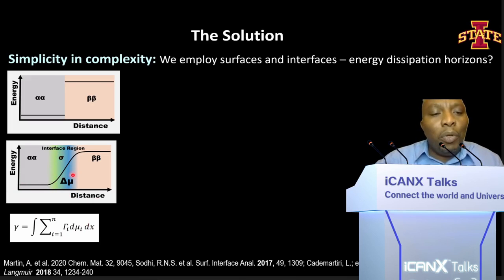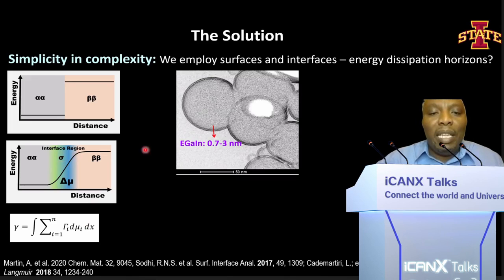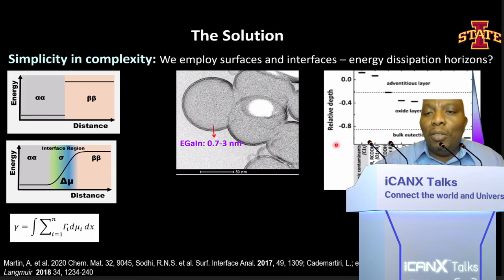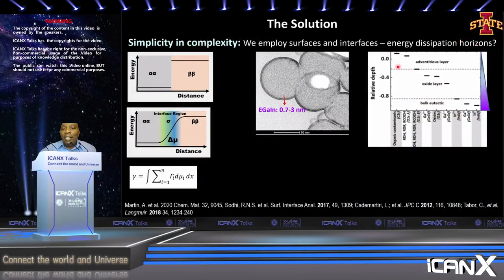If you take this approach to looking at surfaces, then how does the surface of a metal look like? We are not the first to look at this. A few groups have looked at the surface oxides of metals. And if you look at a simple metal like eutectic gallium indium, you find that that oxide ranges from 0.7 nanometer all the way to 3 nanometers. But from this requirement, that there has to be a distribution to create this interfacial excess, how then can we actually describe this oxide on this simple metal? About 10 years ago, we looked into that problem when I was still with George Whitesides, and we found out that actually, even in a simple binary alloy like this, that oxide is not uniform.